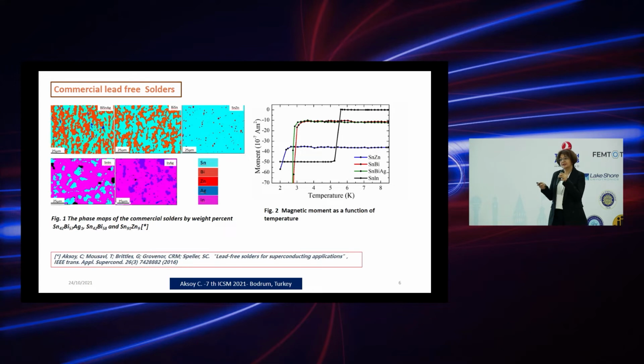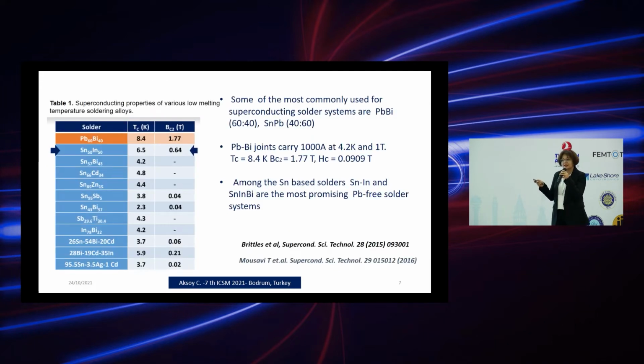What we did before was focus on commercial solders first, to explore whether they are useful for superconducting applications. We found that they can be useful for aerospace applications, but not for the superconducting phase. Then we focused on the literature, and we found that lead-bismuth is quite efficient. It's a leader, followed by tin-indium solders showing good superconducting properties, and then tin-based solders. Lead-bismuth is quite efficient because it carries 1000 amps at 4.2 Kelvin and 1 Tesla.